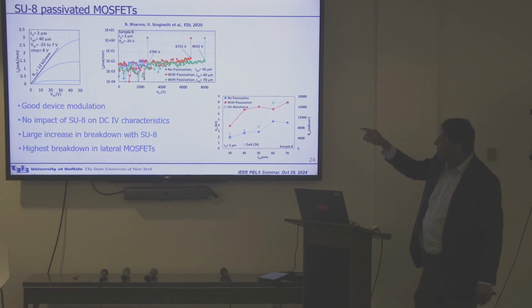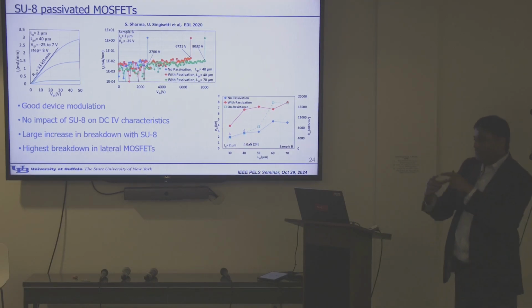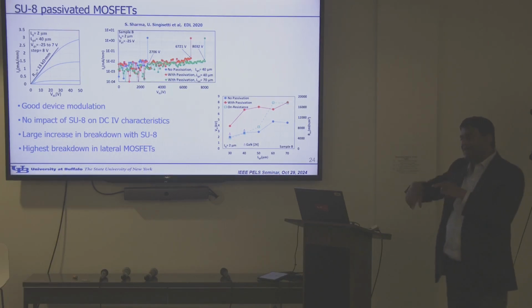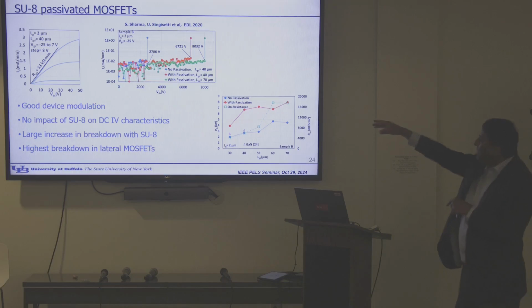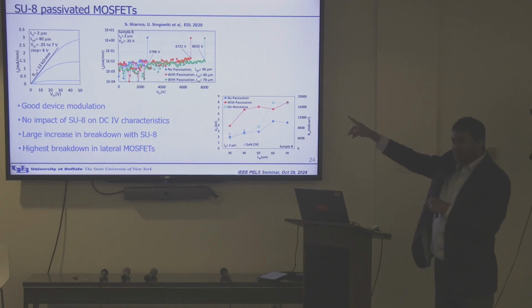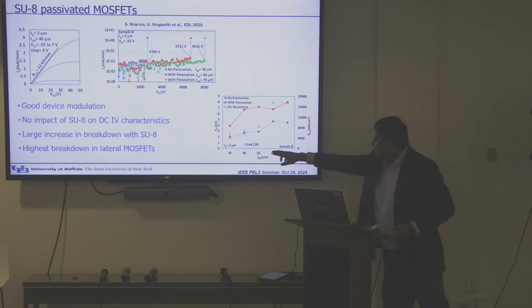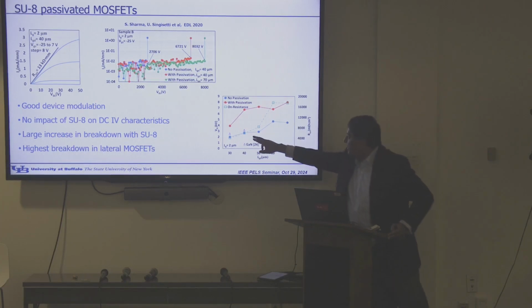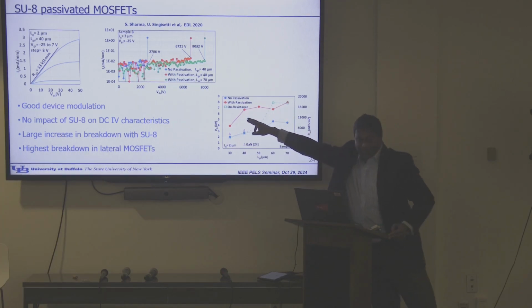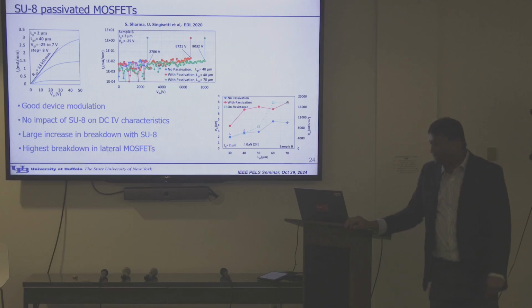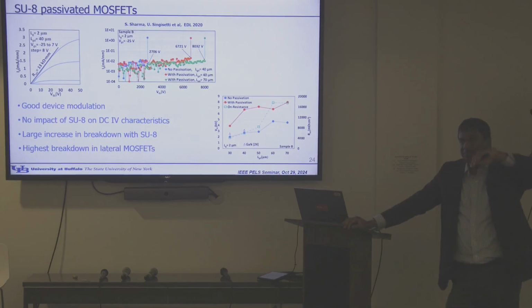But if you see the middle figure here, the blue points, we take the wafer or a piece or coupon, 5 millimeter. We fab the device. Once we finish up, we measure the breakdown, right, and go back to the SU8 process. Come back and measure second row of devices, right? And you can see that from blue to red, there's a big change in the breakdown voltage. Clearly, this is before you did any SU8, and then after you add SU8, there's a big boost in the breakdown voltage, clearly showing that you need to manage the fields on the lateral MOSFETs, right, at the top level.